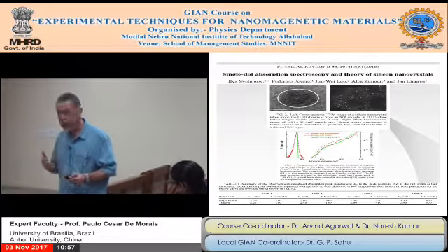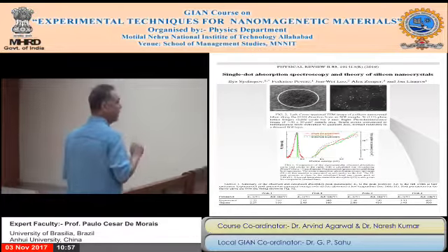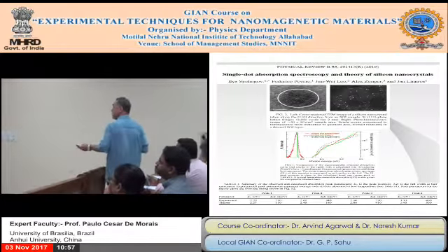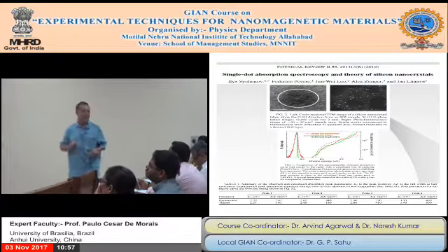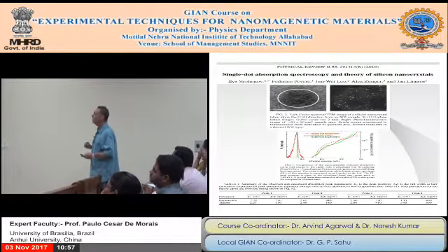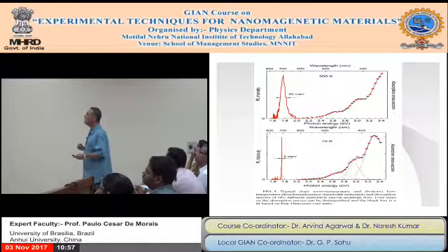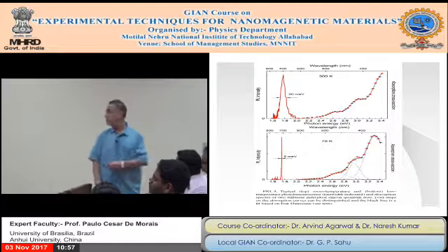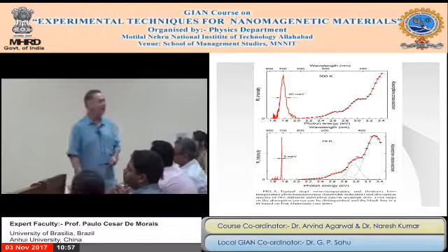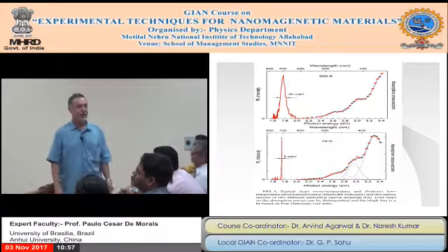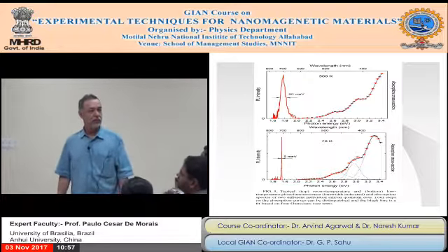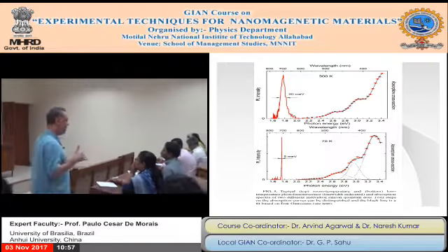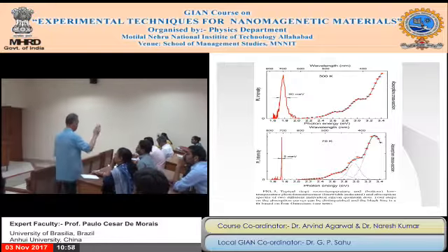So here you can see the same sample but at different temperatures. At 300 K, room temperature, you can see the PL line is quite broad. Look at that, about 90 millielectron volts in line width. If you lower the temperature, then it becomes very sharp, 5 millielectron volts. For PL, if you want to get very good information about energy levels, you better lower the temperature.